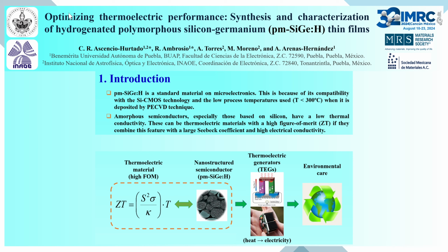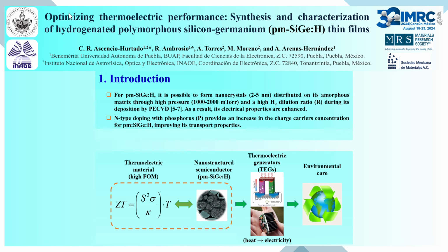Amorphous semiconductors, especially those based on silicon, have a low thermal conductivity but can be used as thermoelectric materials with a high figure of merit if they combine this feature with a large Seebeck coefficient and high electrical conductivity. N-type doping with phosphorus provides an increase in the charge carrier concentration for hydrogenated polymorphous silicon-germanium, improving its transport properties.